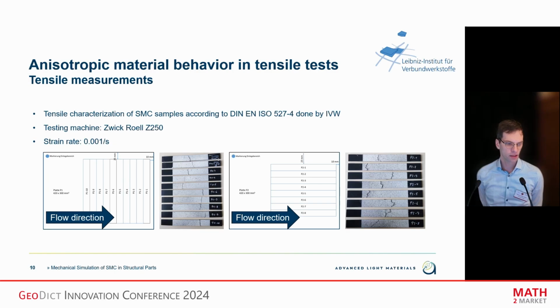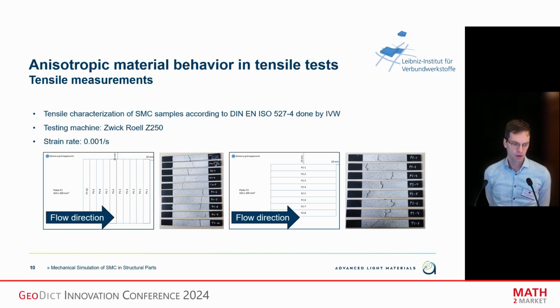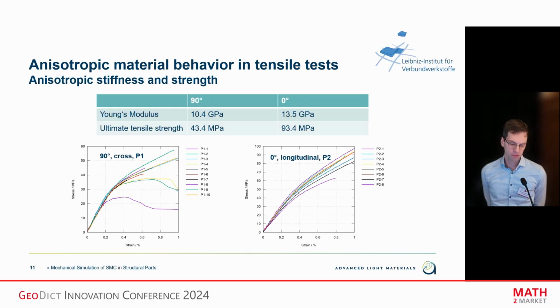Let me continue now with the mechanical characterization. As we saw in the CT scans and also from the process simulation in these plates, we have a slight fiber alignment, and our colleagues at the Leibniz Institute for Verbundwerkstoffe performed some tensile measurements for us at quasi-static strain rates to characterize the anisotropy of the mechanical behavior. And we obtained, actually, there is some anisotropy. The Young's modulus is rather different between the 0 degree and the 90 degree direction. Also, the ultimate tensile strength is quite different between the 0 degree and the 90 degree direction. But you see also from these measurements that the variations between different samples can be very large.